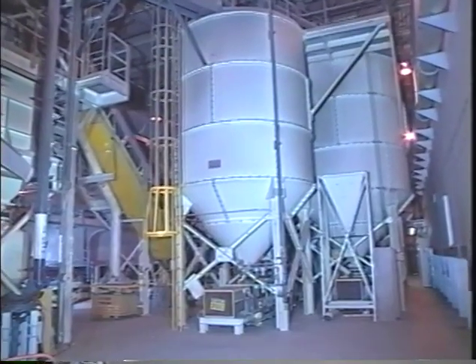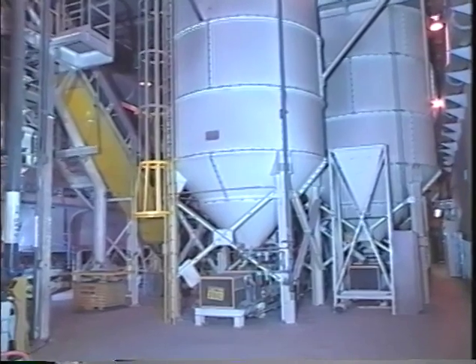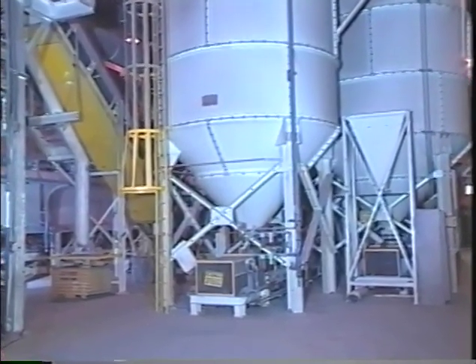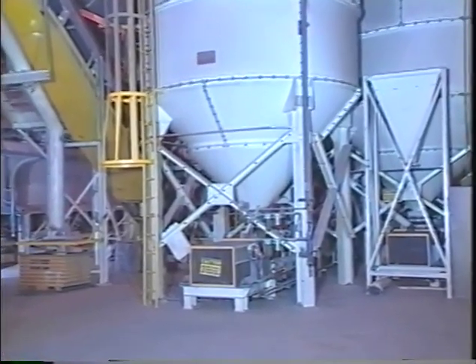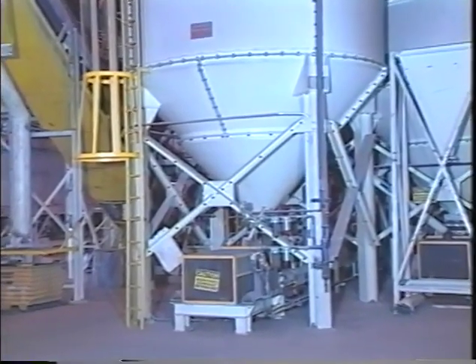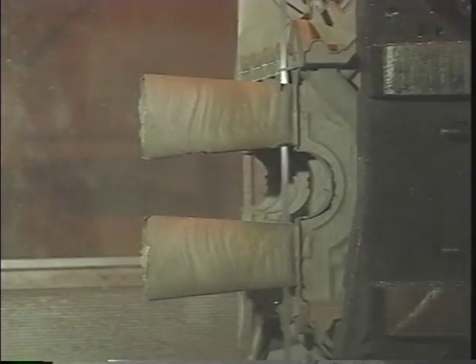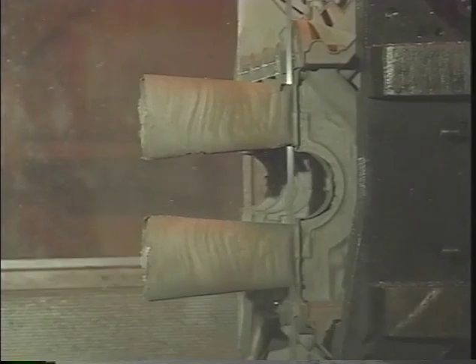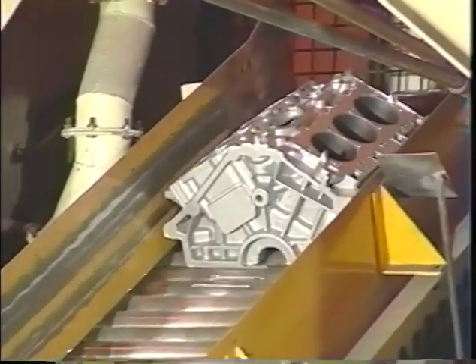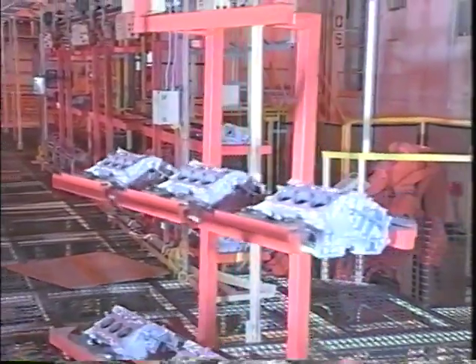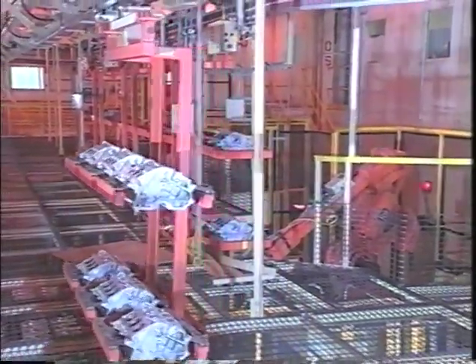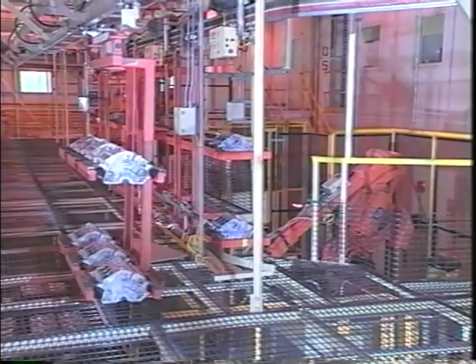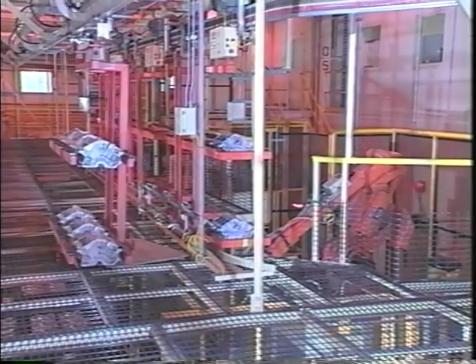The sand is filtered and cleaned. A phenomenal 99.8% of this expensive sand is reclaimed, thus saving production costs and eliminating landfill disposal costs. When the block is unloaded from the TSR, the risers are cut off and the block is shot blasted. After shot blast, the V6 blocks are transported using an overhead electrified monorail system to the material handling for heat treat system.